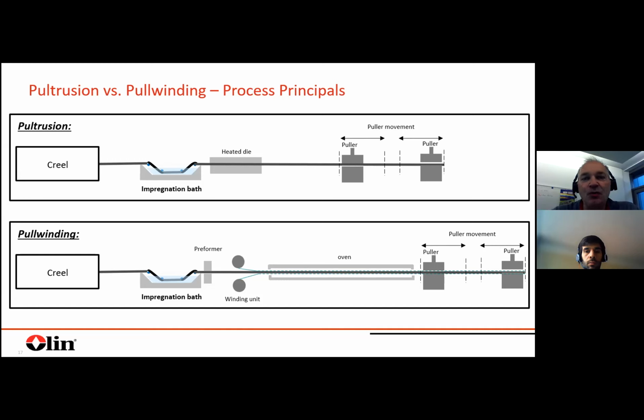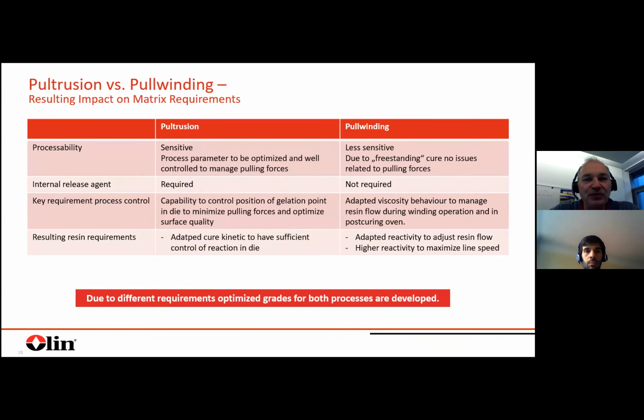So what does it now mean for the resins themselves? If you compare pultrusion and pull winding, first processability. For pultrusion, I would say it's a, let's call it, more sensitive process, because you really have to find a good balance between processability, line speed, surface quality, and so on. And as you cure it in the die, you need a really accurate method to manage the pulling forces, which is also related to part quality or surface quality. In pull winding, as you have this freestanding cure, these issues which are related to the closed die are not existing. So from a processability point of view, pull winding is much more robust. It has a bigger process window. It's not so sensitive to distortion and so on.